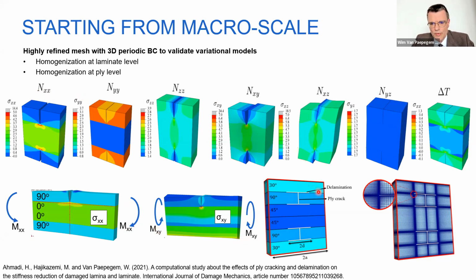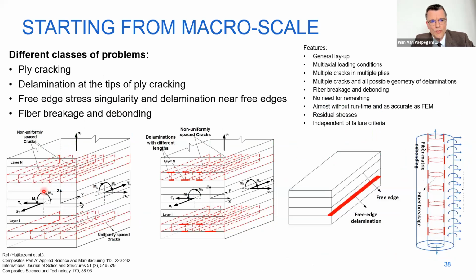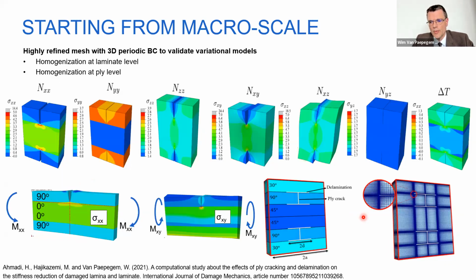And you even see a very detailed RVE with ply cracks, delaminations from the ply cracks. And then we apply not only in-plane loading, but we can also apply curvature, so second order periodic boundary conditions, and then look at the local stresses and the homogenized behavior, and compare it with the solutions we get from here. And this we have done over the years very extensively, so these models are fully validated.